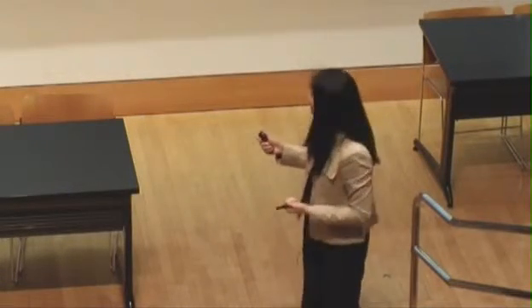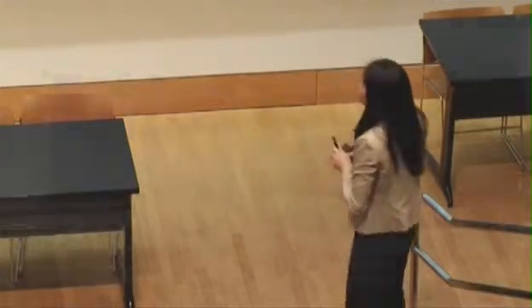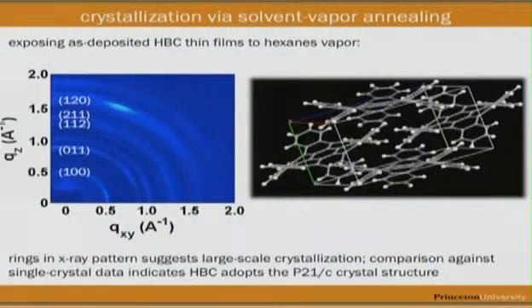So to look at this further, we employ a lot of X-ray diffraction. So this is an X-ray diffraction pattern. We collect these at the synchrotron. So the students actually go to Cornell, where there is a synchrotron, and they run these experiments. These experiments basically give us quantitative information about the structure. Okay? So if we have HBC that's amorphous, and we expose it to this organic solvent vapor, we get an X-ray diffraction pattern that looks like so. You can see rings, and the fact that you can see rings indicates that this film is actually crystalline. There's now long-range order. Okay?